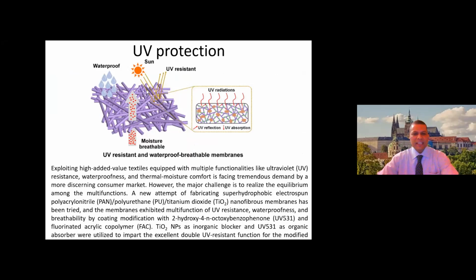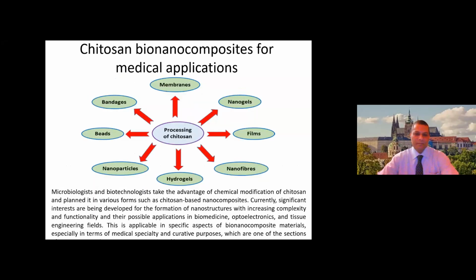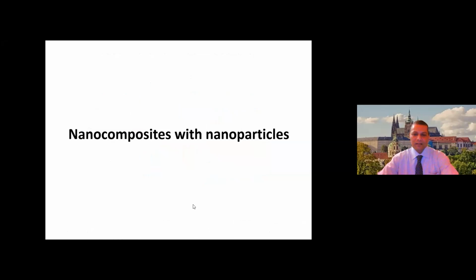UV protection can be achieved by adjustment of the pores, so that the visible wavelengths of light can definitely pass through, but UV light doesn't pass, and this is by some coating of titanium dioxide based nano material, and we are able to have protection against UV light, though we cannot cover from head to toe, but some part of the body can be protected. We can use inherently antimicrobial materials in nanoscale, like chitosan, which is naturally available from sea animals, can be made into nanostructure by mechanical action, ball milling, and then we can use them into certain coatings and finishing, and thus having enhanced antimicrobial property by nanoscience.